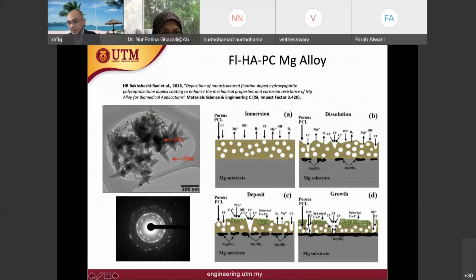This one, another magnesium project, and this time around we use fluorine to dope magnesium alloy. So deposition of nanostructured fluorine doped hydroxyapatite polycaprolactone duplex coating to enhance the mechanical properties and again corrosion resistance of magnesium. So you can see that we can get apatite growth. So immersion. You have the magnesium substrate with the porous PCL, polycaprolactone, and then the dissolution of the PCL and the emergence of magnesium hydroxide. And then you have the deposition of calcium phosphate based material and its growth.